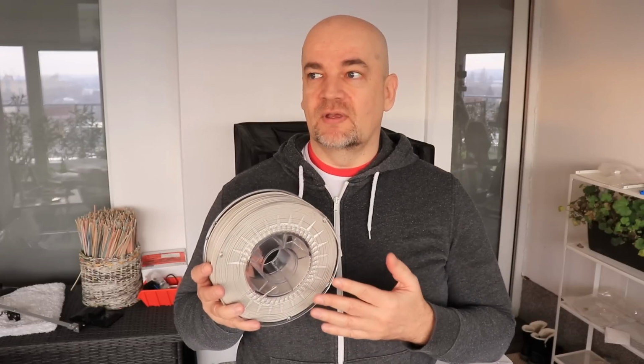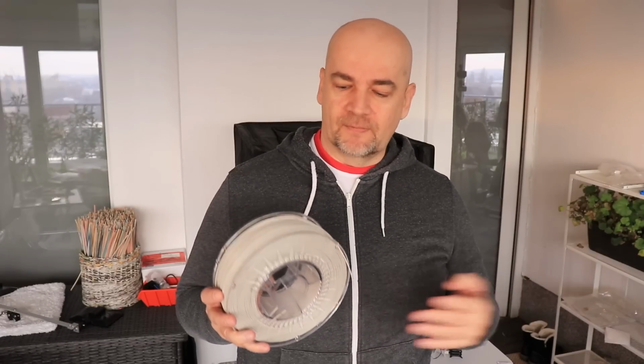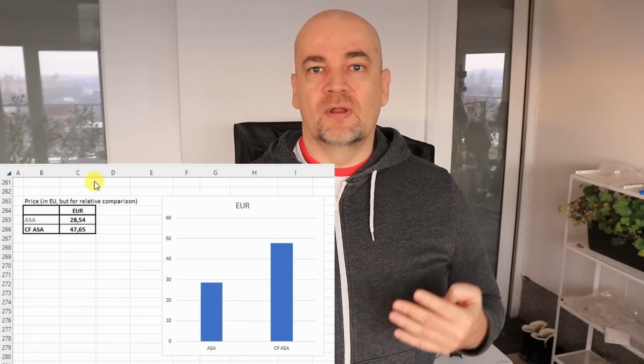ASA is actually my favorite material type. It has even less fumes compared to ABS, and it is great that now we have a carbon fiber version of the ASA. Now, looking only at the mechanical properties, these two materials are very similar. A bigger difference I can see only on the IZOD impact test, and here the regular ASA performed better. And of course a bigger difference is in price, so the carbon fiber version is more expensive.